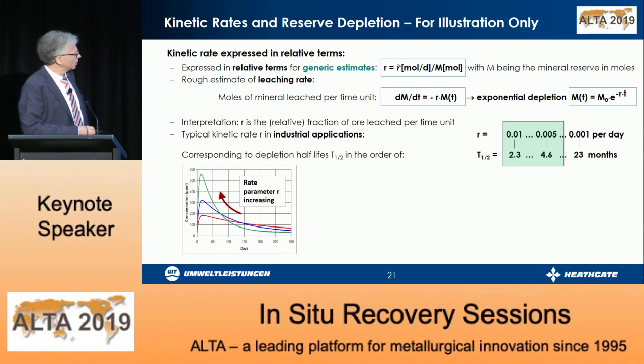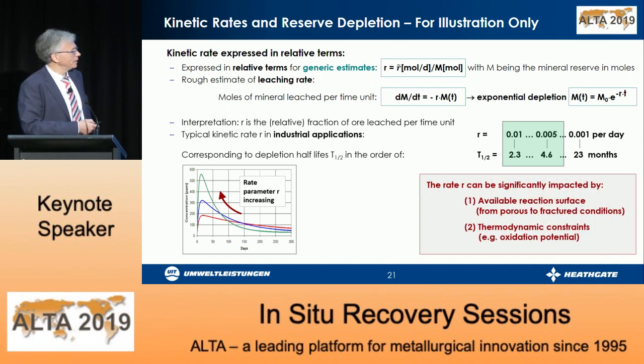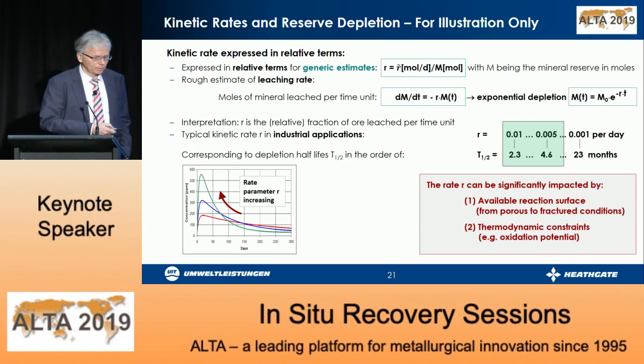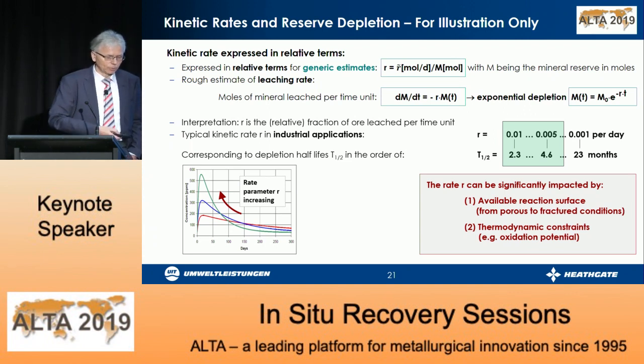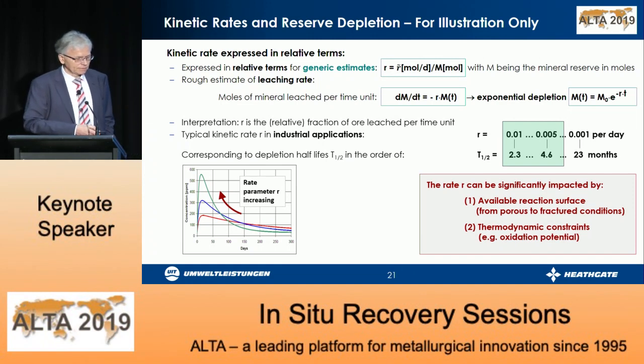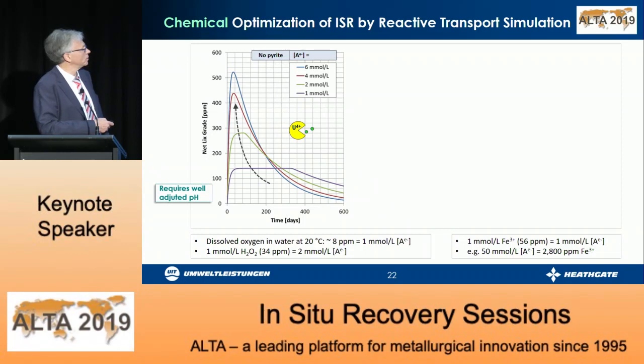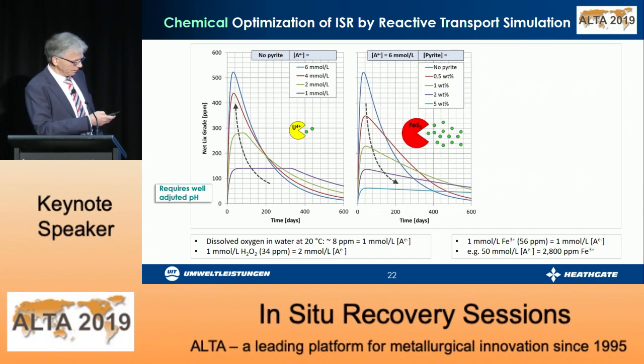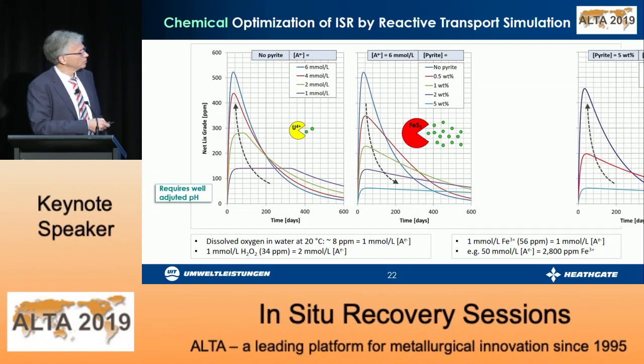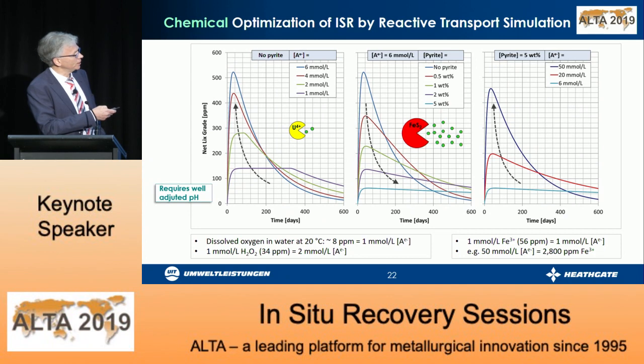Again, you see here the rate parameter effect on the lifetime of the wellfield operation. The rate R can be significantly impacted by the available reaction space, ideal for porous conditions, critical for fractured conditions, and second by thermodynamic constraints, including the availability of the oxidation potential. Here you see the effect of the rate parameter again that can be impacted by increasing pyrite concentrations, and in order to overcome the impact of pyrite, for instance, you have to increase the injected oxidation potential, and then you get back to favorable production conditions.